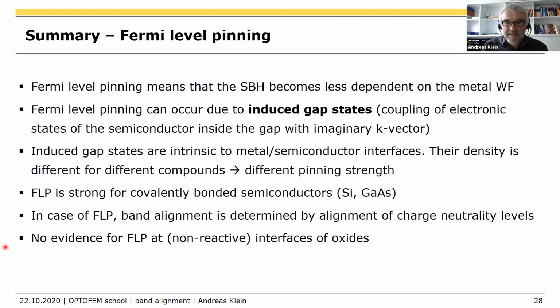Okay, but otherwise, as I said, usually ionic materials do not necessarily have a low density of interface states, but the interface states are near the band edges. And that gives you not much pinning because you can usually move the Fermi level in between quite easily. Okay.